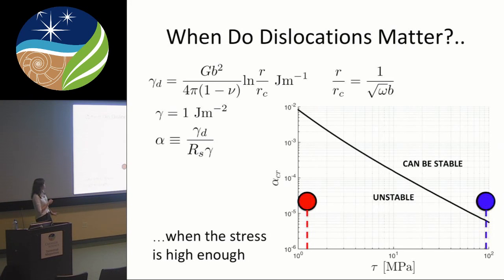I'm not going to go into detail, but just to say that there are models that can tell me what these energies are. And so what we looked at is what is the critical alpha. Basically, how strong does this parameter need to be in order for the dislocations effect to matter? And this alpha will depend on stress. So you see stress on the x-axis here and critical alpha here.